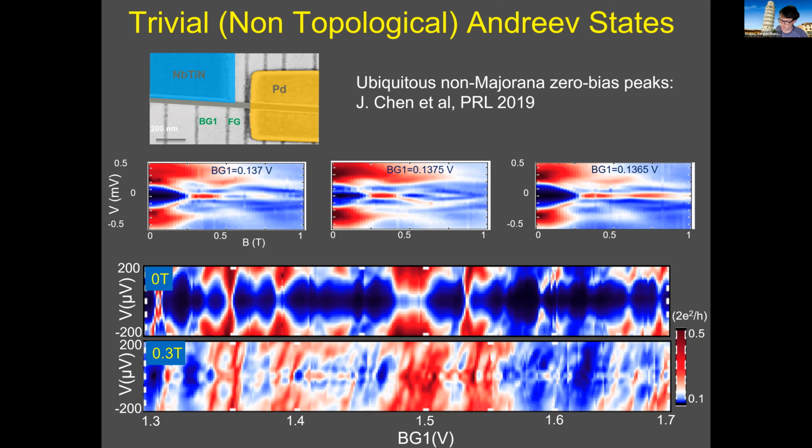Why is the appearance of a zero bias peak never correlated to closing and reopening of the gap? Yes, closing and reopening of the topological gap is another signature that would be nice to see, and I could add it to the list on my signature slide. Absolutely. Then why is it not seen? Well, maybe because we've never reached the true topological regime in these wires, or maybe because it's not visible since it's in the middle of the bulk, as some theories suggest.